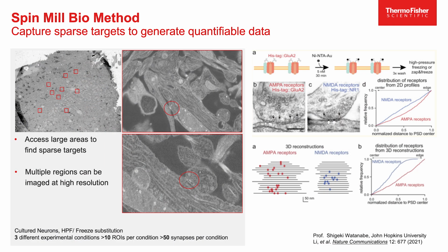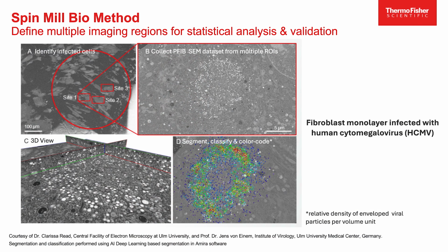And the other aspect is that you can combine spin mill with multi-imaging facets. That means that for each region of interest, you might use different imaging settings. So you might have an overview at a lower resolution, and then you can just zoom in and have a sub-volume at a super high resolution. It's really very flexible, and I think this can push further the options for generating more statistically validated data, because now you can very easily compare different subsets of features, or you might really compare treated against not treated samples.